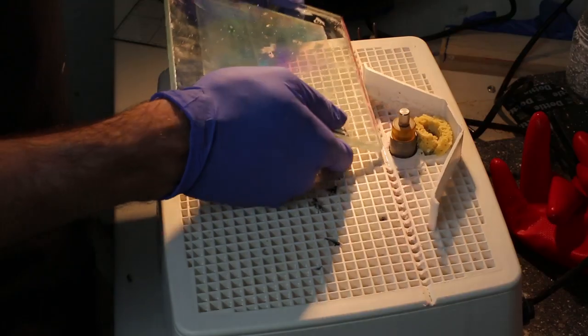Always keep in mind that the wider the rim between the emulsion and the actual edge of the glass, the longer your hologram will last. The humidity in the air will eventually destroy every DCG hologram, but the wider the rim, the more distance the moisture has to penetrate before it can reach the emulsion.